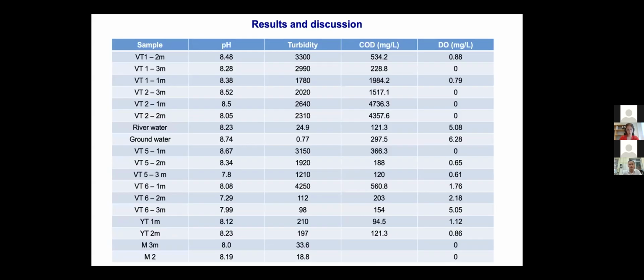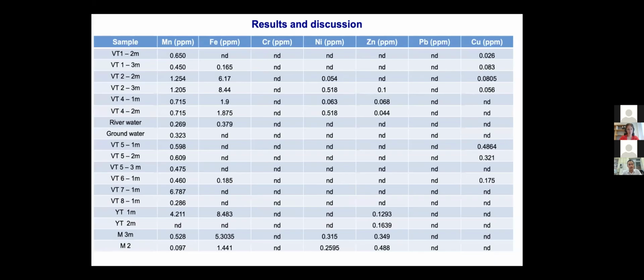And here are some results about the pH, turbidity, COD and DO in different dump sites and landfills. We collected the wastewater, and we see the pH is around 8. The COD is almost all higher than the limit, and mostly the DO, the dissolved oxygen, is very low. We also analyzed the heavy metals. As you can see in the table, the concentrations of heavy metals are very low, so almost no concern about heavy metals in the dump sites and landfills that we studied.